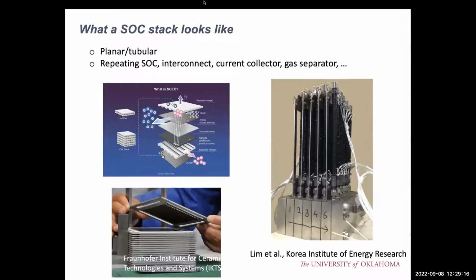And so what it looks like for the SOC. The top one shows all the components for the SOC. As you can see, one unit consists of the two electrodes, anode and cathode, and in the middle is the electrolyte. And in order to lay many pieces of the SOC together, we need to put the interconnector, separator, in the middle of each cell, so we can collect the current density, voltage, and we can also feed different kinds of gas like the steam and the carrier gas into the different sides of the electrode.